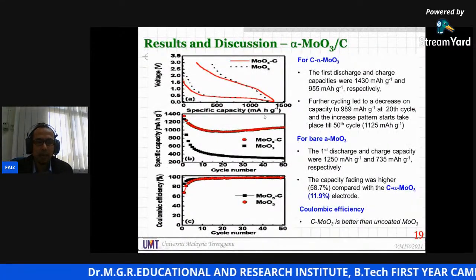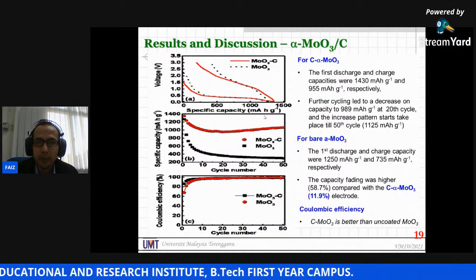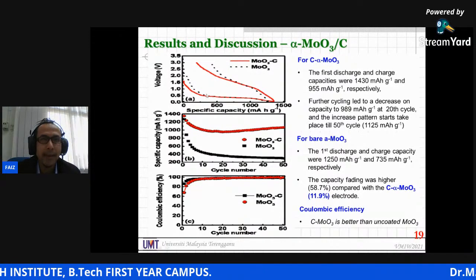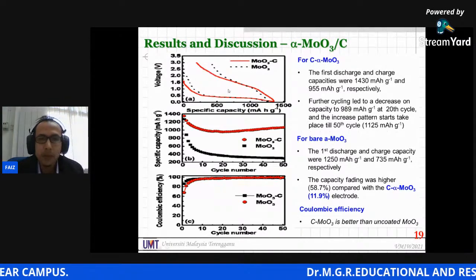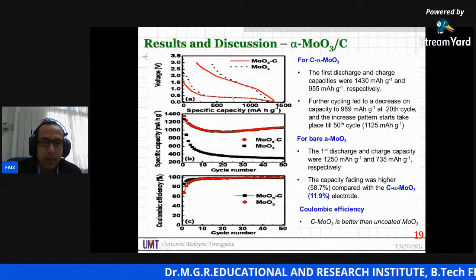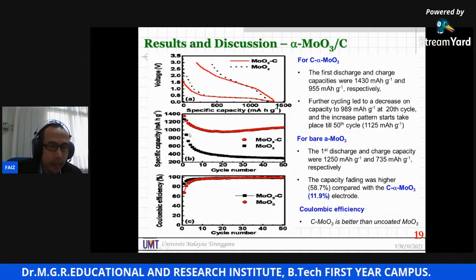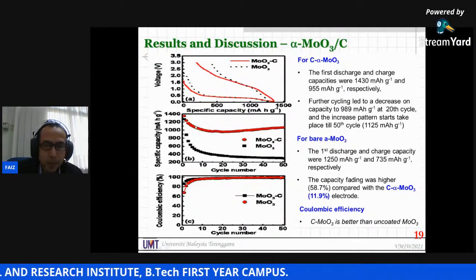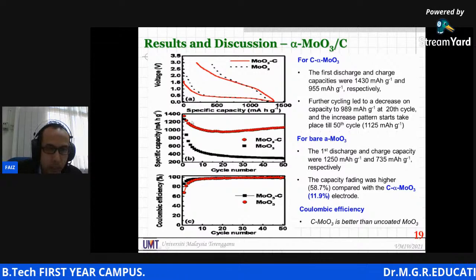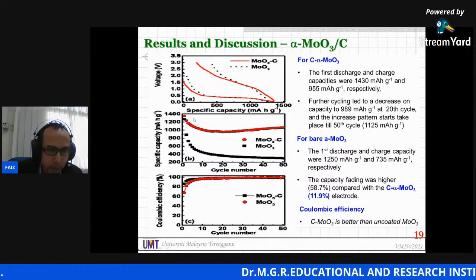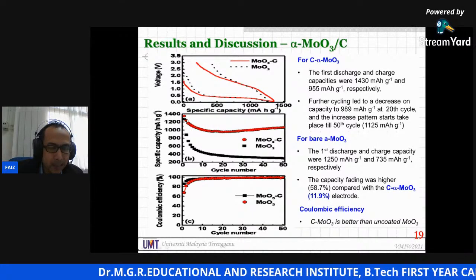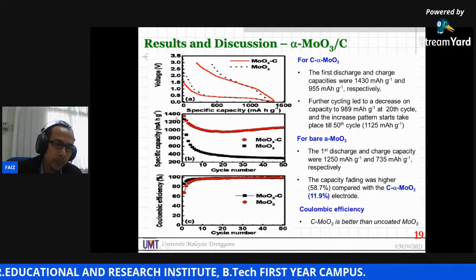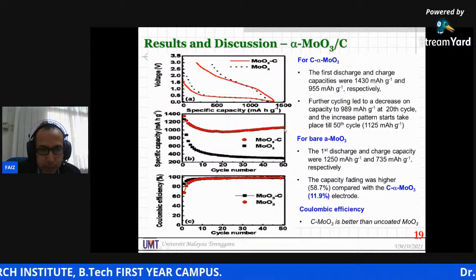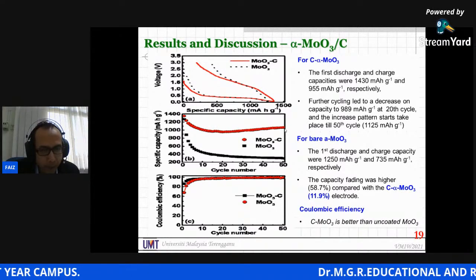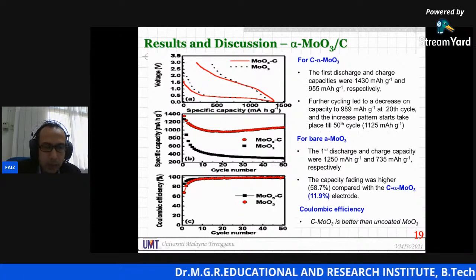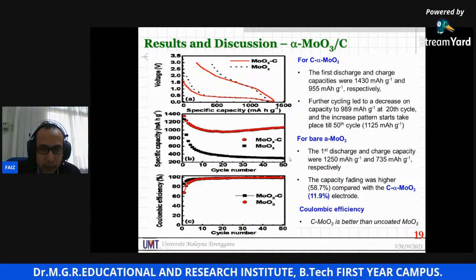So this is one of the electrochemical results based on carbon-coated molybdenum oxide. As we can see from here, the red color corresponds to the carbon-coated molybdenum oxide curve. As can be summarized here, the carbon-coated molybdenum oxide had the superior electrochemical activity in terms of capacity. Starting from the first cycle, it has a capacity of almost 1,400 milliampere hour per gram. And after 50 cycles, we can see that it still maintains a very good capacity of more than 1,000 milliampere hour per gram, compared to without carbon coating.